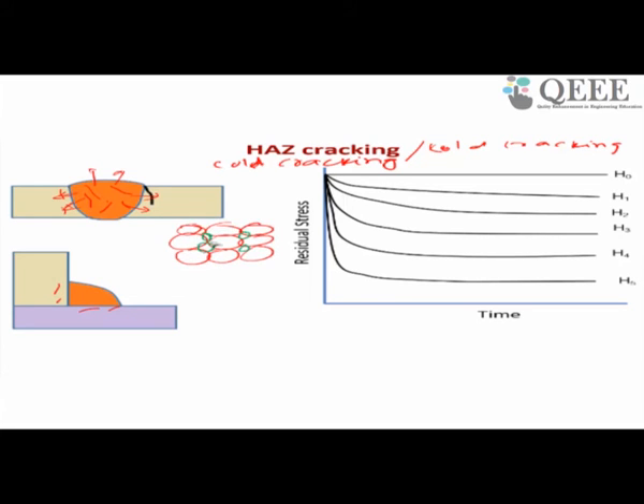Suppose these are the atoms, and since hydrogen is fitting inside the regular atomic structure, it will create a stress field around it. During solidification, hydrogen came out from the weld and is entrapped mainly in the zone nearest to the weld metal zone, which is called the heat affected zone, and it will cause a stress field around it.